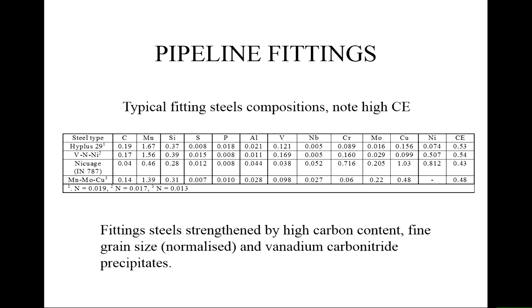The grain size is fine, but not as fine as controlled steel, so we get that as small as possible by normalising, and then we add the vanadium to form carbide precipitates and a bit of nitrogen, so they become carbonitride precipitates to give us extra strength. So you work harder with fittings to get the same performance.